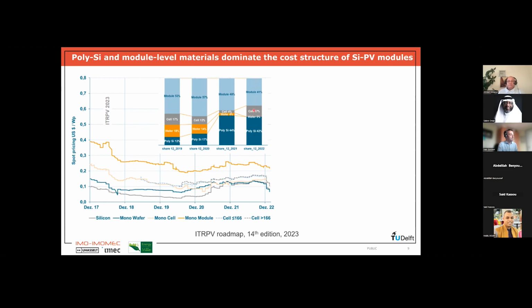And if we look now at this inset, so this is for the end of 2022, we see that of this 23 cents, around 40% of this cost is directly related to the polysilicon that we are using. So actually, the silicon material, which needs to be very pure, and the wafers need to be almost defect-free. To achieve that, we really already have to pay a high cost. So around 40% of the total module cost simply already comes from this silicon material itself.